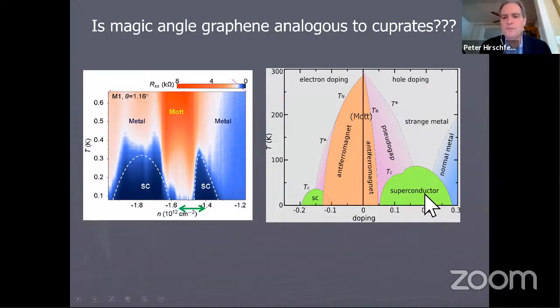This time I've shown not only the hole doped superconductors to the positive range of doping, but also the electron doped superconductors to the negative range, and compared now with what is seen in the device containing the twisted bilayer graphene, where you control the doping with a gate. And you can tune the system from a superconductor in a certain range of doping to a Mott insulator, which is not a superconductor, it's not even a metal, and then back to a superconductor and then to a metallic phase. So this is a really wonderful playground for superconductivity, and the analogies are very striking. I don't think they're completely established yet, but that's really a very active field at the moment.